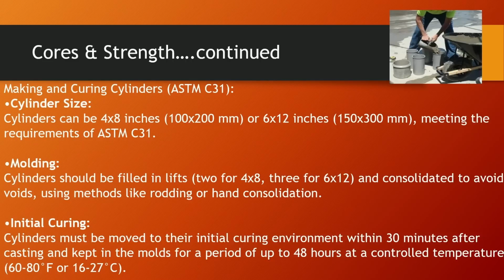Initial curing, cylinders must be moved to their initial curing environments within 30 minutes after casting and kept in the mold for a period of 48 hours at a controlled temperature. So that is how they're going to do it. In that upper right hand corner, you're going to see a gentleman preparing the cylinders, and that's what it looks like.